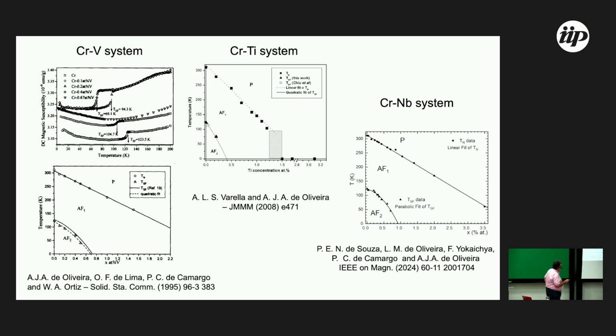The other sister, chromium-titanium, is more interesting. Titanium is on the left side of vanadium, two electrons less than chromium. The behavior decreases linearly, however, at 1.2% titanium in chromium the transition disappears. It's not continuous, it's an abrupt jump here. Okay? In the AF2 phase it is similar, a parabolic behavior. In chromium-niobium, niobium is exactly the 4d metal down from vanadium in the table. It is a similar behavior, a parabolic behavior in the spin flip transition. Okay? I published this result recently in 2024.